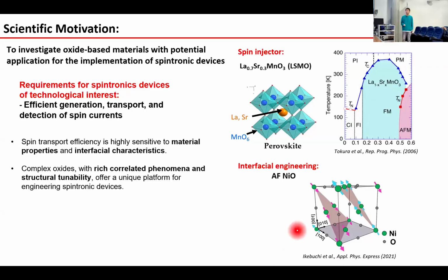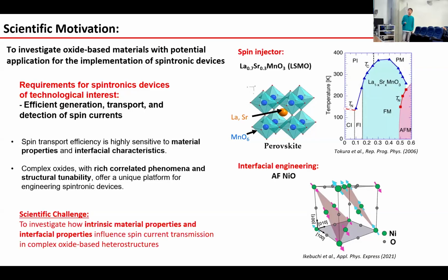For the material choice, we utilize a typical antiferromagnetic material, nickel oxide, which has a relatively high Néel temperature, well above room temperature, and also a relatively simple FCC structure. So the scientific challenge is to investigate how the intrinsic material properties and the interfacial properties influence the spin current transmission in complex oxide-based heterostructures.